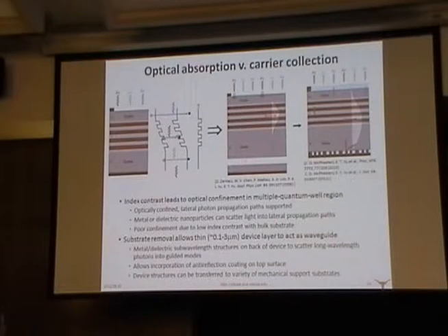What we did initially was to look at structures like this and recognize that in the quantum well regions, they have a smaller band gap, and that is accompanied by having a larger refractive index. This idea is well known in, for example, the semiconductor laser community. It's used for guiding of laser modes.